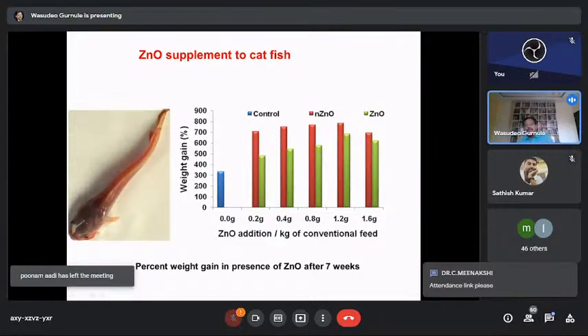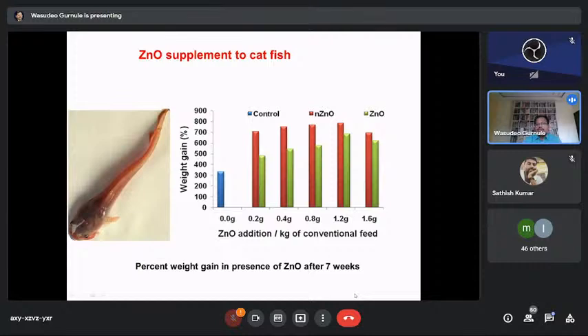One experiment we have carried out shows that this zinc oxide can also be used as a supplement for catfish. Here, red color shows nano size zinc oxide, and blue color shows the control. By addition of zinc oxide only, we have observed an increase in weight, here after 7 weeks, of this catfish. So zinc oxide can be used as a feed.